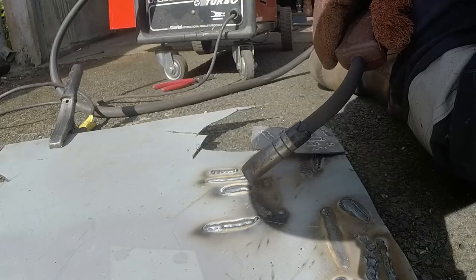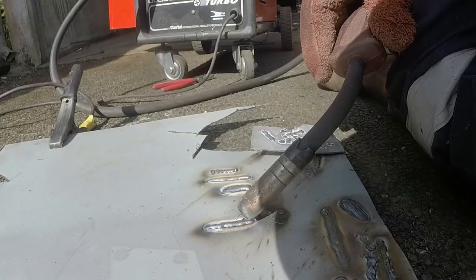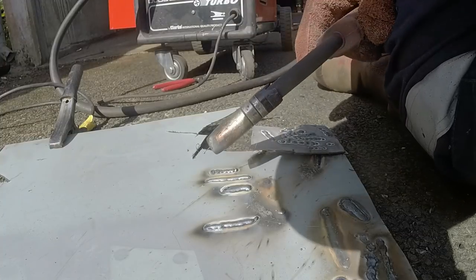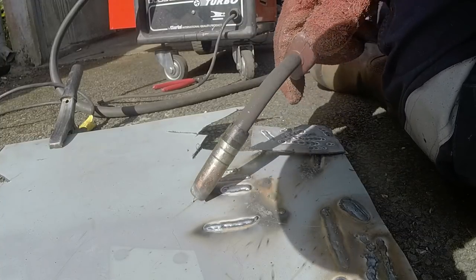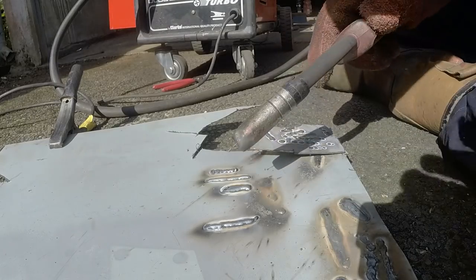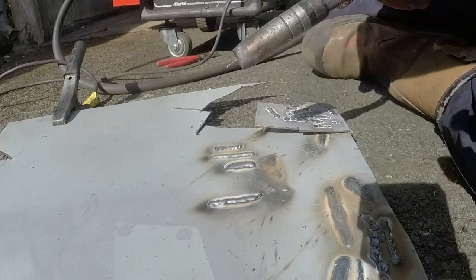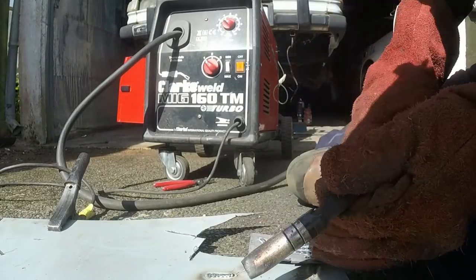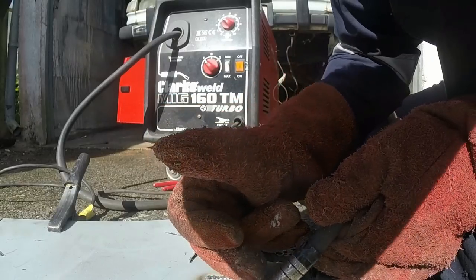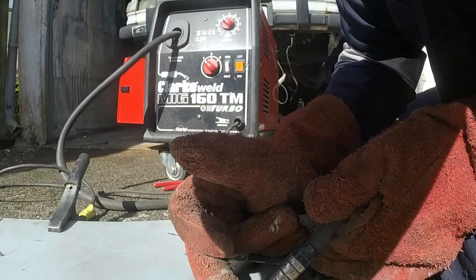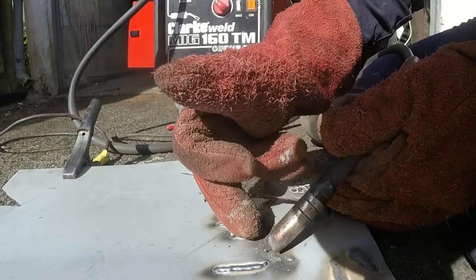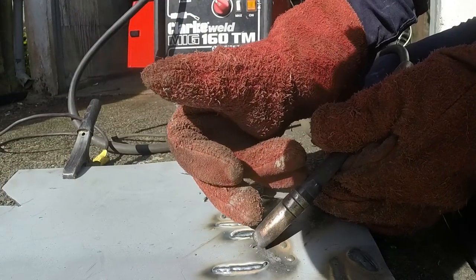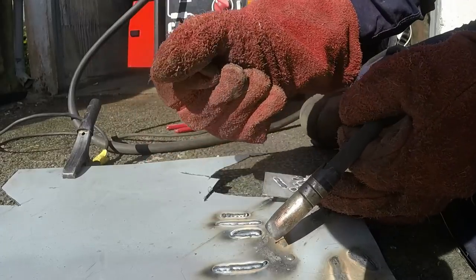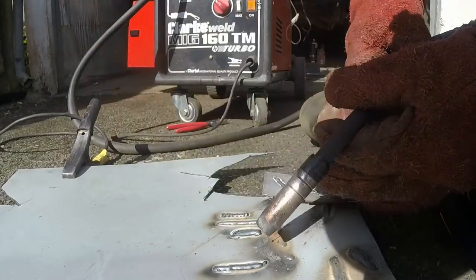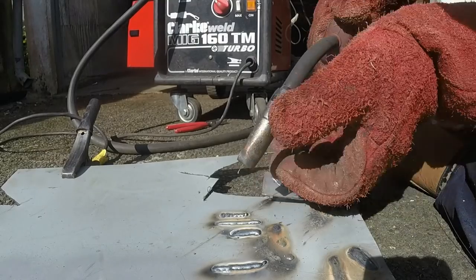it's marginally hotter and it's sat down a little bit deeper into the surface. I'm going to show you what happens now if you have your wire speed too slow or too fast. So all the same settings again, but I'm going to turn the wire feed right down. And what will happen is, because the wire is coming out too slow, it'll be arcing and then that bit will burn away and drop off. Then the next bit will come out, arc and make a weld, and then burn back into the gun and drop off. And it will probably go like bzzzt, bzzzt, bzzzt, even though I'm holding the trigger down the whole time.